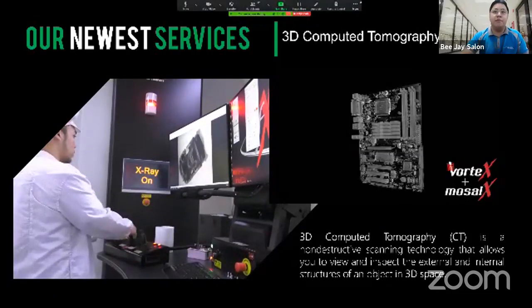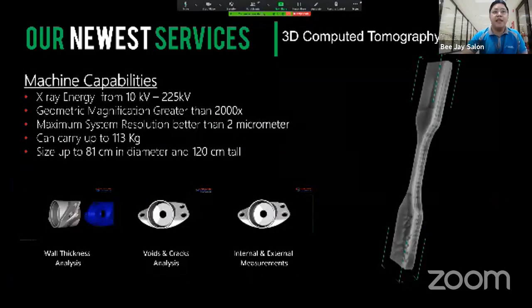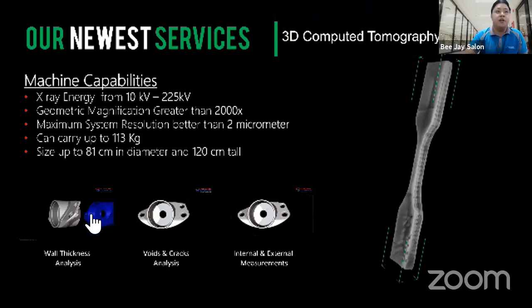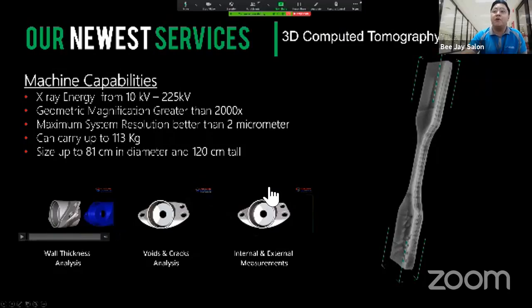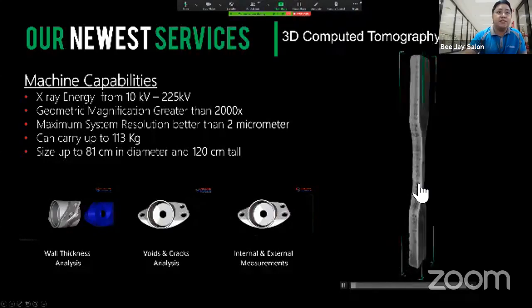Our machine is capable of having an energy from 10 kV to 225 kV. It can penetrate at least 2 inches of steel and 8 inches of aluminum, while its geometric magnification is greater than 2,000 times, while the maximum system resolution is better than 2 micrometers. It can carry up to 113 kilograms, and we can analyze samples up to 81 centimeters in diameter and 120 centimeters tall. So as you can see in this video on your screen, this is a 316L stainless steel